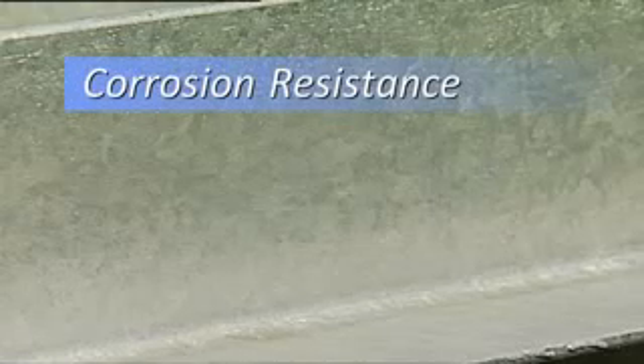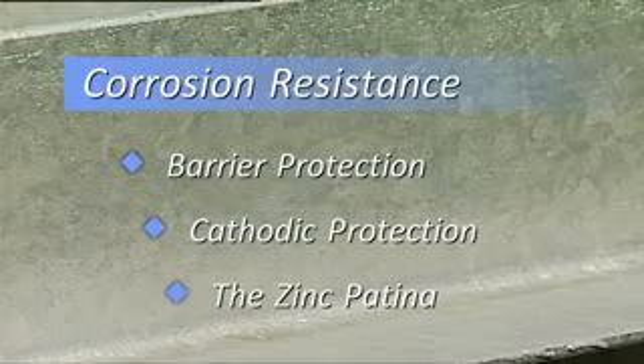While hot-dip galvanizing is primarily specified for its superior corrosion protection, it may also be chosen for its durability, maintenance-free longevity, environmental sustainability, and aesthetics. Steel is an abundant and efficient building material, but when exposed to the atmosphere, it immediately begins to corrode. The hot-dip galvanized coating provides 3 levels of corrosion resistance: barrier protection, cathodic protection, and the zinc patina. The hot-dip galvanized coating effectively protects steel from the environment, providing barrier protection. Galvanizing also provides cathodic protection, meaning the zinc will corrode first to protect the underlying steel. Even if the coating is scratched, the surrounding zinc will continue to resist corrosion of the steel. As zinc is exposed to the environment, it naturally forms byproducts on the surface known as the zinc patina. The zinc patina further slows the corrosion rate of the zinc and acts as an additional environmental barrier.